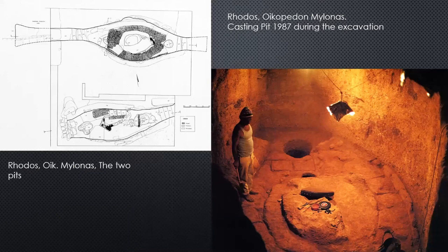The next, please. The cleaning of the bigger pit showed that the casters had cast another larger than life statue here. The pit had originally been completely isolated with mud bricks, the casting mold being installed in the middle. The actual firing room was closed off by walls on both ends of the pits. Allowing ideal heating conditions, the wax that was flowing out during the heating was led through the channel underneath the partitioning wall and collected in a small pit.